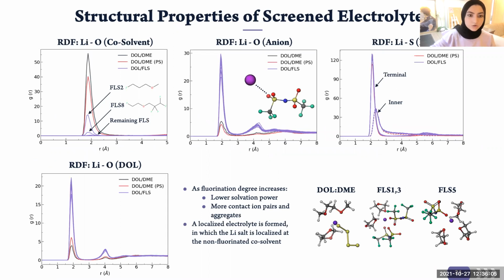The radial distribution functions, which are shown in this plot, reflect the coordinating strength between the cation in the electrolyte and other atomic components. For example, for the coordination with the co-solvent, which is either DME or one of the fluorinated solvents identified in this work, we found that the strongest interaction occurs with DME, and there is a monotonic decrease in the coordinating strength with the fluorinated solvents as the degree of fluorination of the solvent increases. And this can be attributed to the additional steric hindrance introduced when adding the CF2 and CF3 groups on the fluorinated solvent. Despite the presence of the ether oxygen atom here, there is a strong electron withdrawing effect of the fluorine atoms that largely reduces the affinity of the solvent towards the cation.